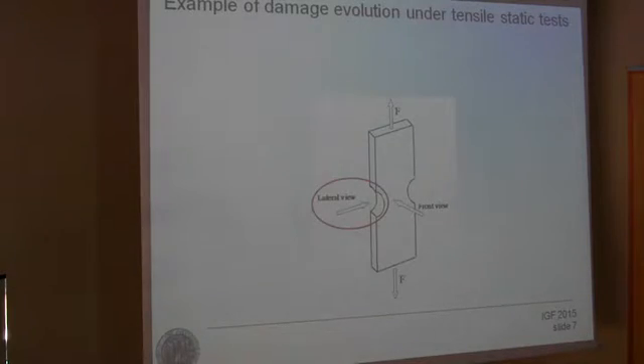In order to understand the damage evolution in the case of static tests, we observed the specimen from two different points of view: the lateral view, that means we look inside the notch tip, and also the front view. We found that the most useful results came from observing the specimen from the lateral view. This is shown as an example. This is the completely recycled polypropylene in the case of 10 millimeter notch radius. This is the notch tip looking from the lateral view.